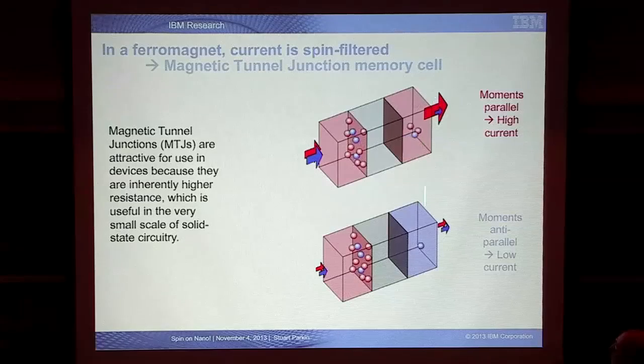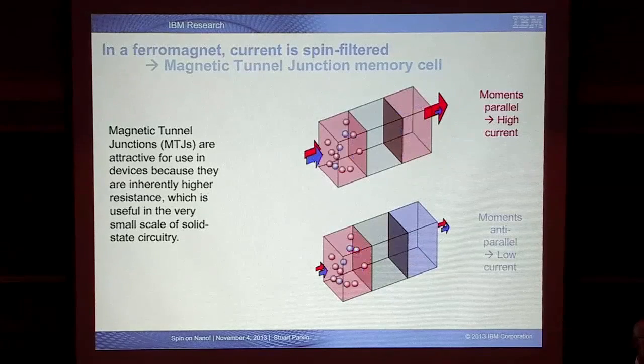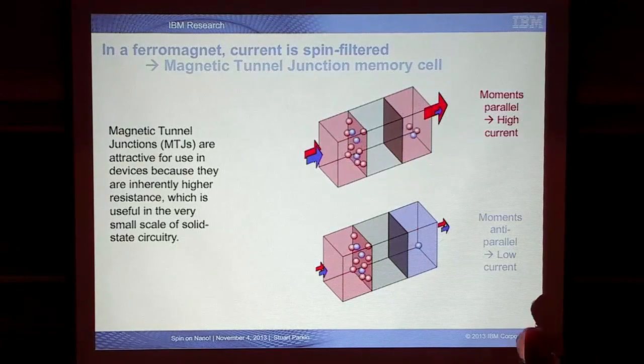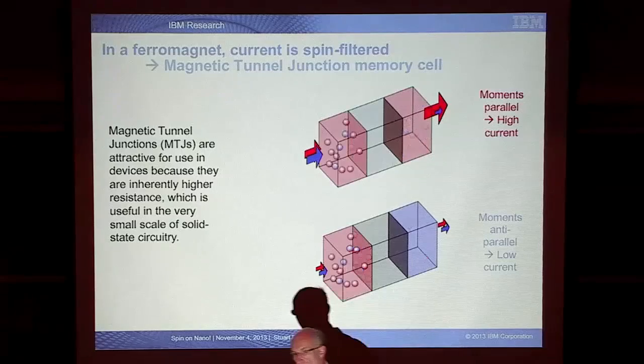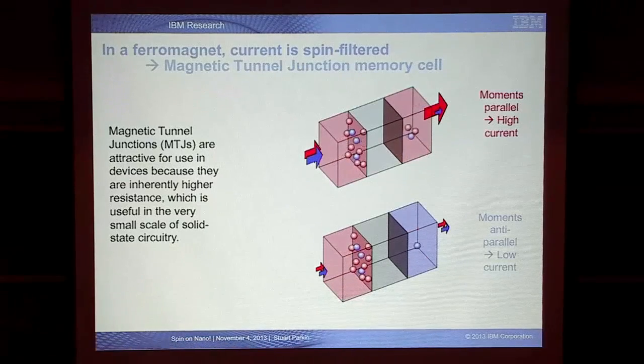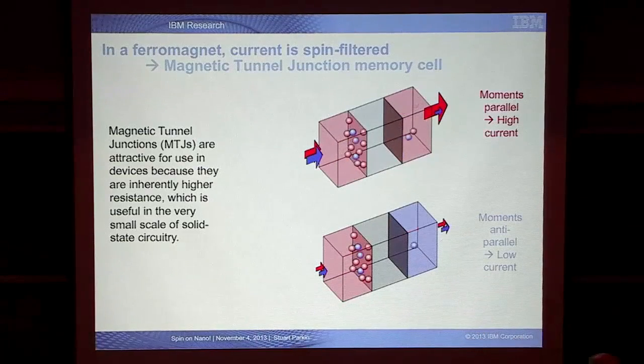Now the change in the tunneling current can be up to a factor of 10 at room temperature. It's much bigger. It's not a vacuum, it's going to be an insulating material. Typically, it would be, for example, aluminum oxide. And I'm going to show you, using magnesium oxide, we can improve things. It could be vacuum, though. That's certainly possible. Essentially, it's just a material in which there are no electronic states.